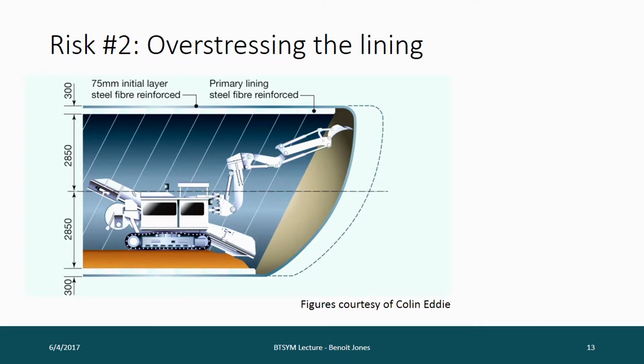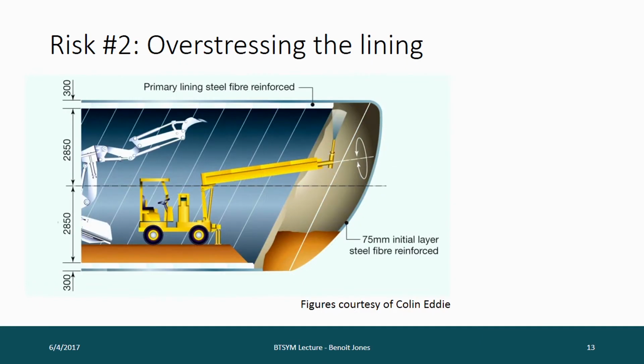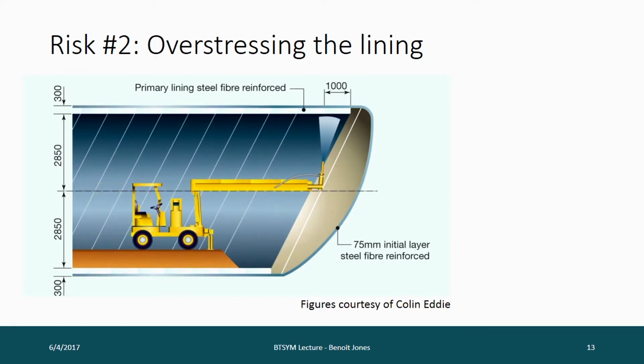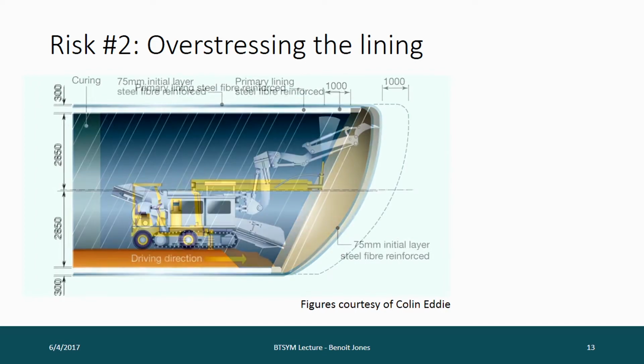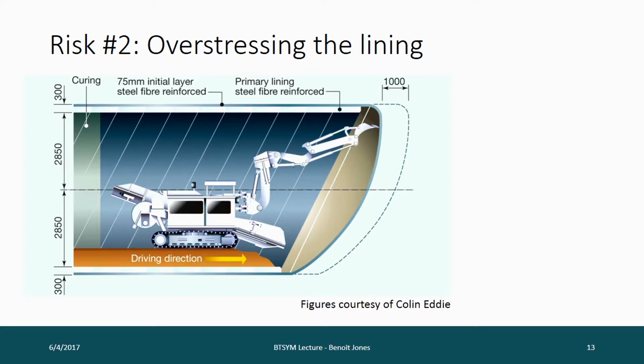So what we tend to do is we measure the strength and we hope that we've done the workmanship well. So the other risk, overstressing the lining, comes about because shotcrete, obviously, when you first spray it, has very little strength. So we excavate, we spray a sealing layer maybe, and then we spray a primary lining. And then the next thing we do after that is to start excavating the following advance. And as soon as you start excavating the following advance, you get front to back arching of the ground and you start loading very lightly at first that ring of shotcrete. And then as you continue to advance beyond that point, more and more load comes onto the shotcrete lining.